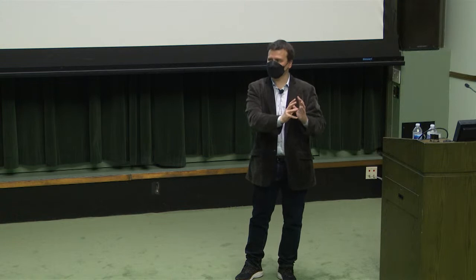No. So initially, back then, the fact that it occurred at an integer filling factor meant the closest thing that we found was Mott-like type of physics. What is becoming clear now is that there is a phase transition taking place at each integer number of electrons per Moire unit cell to a broken symmetry state, and that broken symmetry state is what becomes an insulator at each of those integers. So it's still due to strong interactions, but I don't think you can call it a Mott state because you're actually breaking the symmetry. I see, thanks a lot.